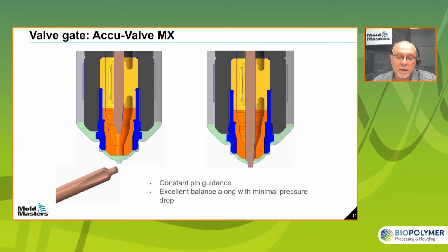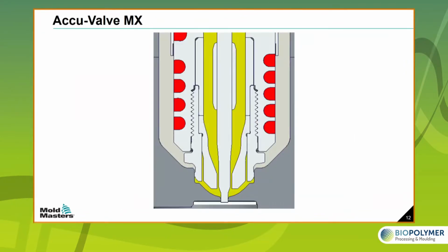It has constant pin guidance, guiding that valve pin into position, and the close tolerance on the valve pin and the gate ensures that we achieve a high gate quality. So the valve pin is pulled back through an actuation mechanism, typically hydraulic or pneumatic is more commonplace, pulling that valve pin back, opening up clearance for the plastic to flow through the nozzle and into the gate.